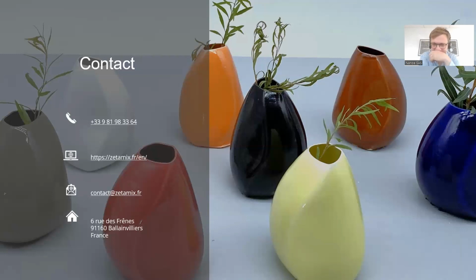So a few questions here. Since we have questions in French, I'm still going to answer them in English because we have a few English-speaking people. So how thin can we print with this technique? It's FDM, so we print like standard FDM. Typically, we've printed layers of 0.1 to 0.3, and the smallest wall thickness we've done so far is 0.4 millimeter. So that's really very, very thin.